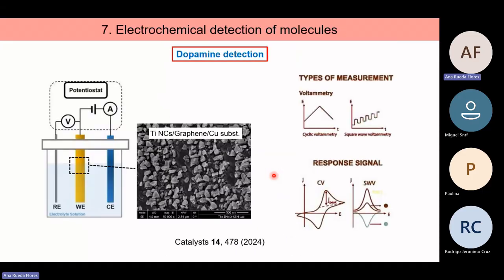A third application in the biomedicine field is the detection of molecules. In this case, we would like to detect dopamine. In this example, dopamine is the so-called molecule of pleasure because it's involved in the regulation of our mood. So the idea is that in the standard 3-electrode cell, in the working electrode, we will have our nanocolumns, in particular titanium nanocolumns, on top of graphene, on top of a copper substrate.